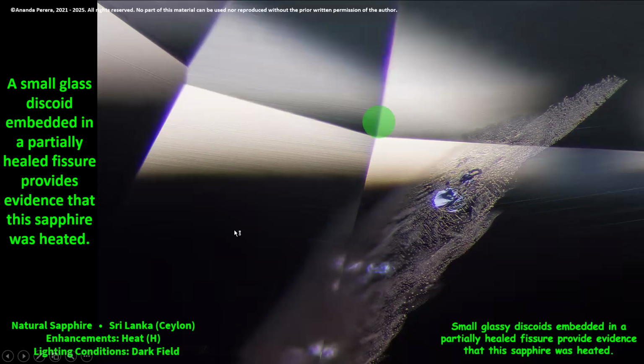When we go here, what are the lighting conditions? Only one. It is dark field. Under dark field illumination, this heated Sri Lankan sapphire tells us a lot of things. Small glassy discoids embedded. See, one is here, another one, another is there. Those are glassy discoids embedded in partially healed fissures.